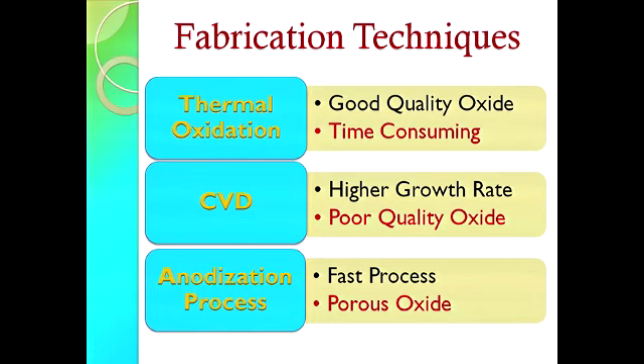We know some oxidation techniques that can be used to form silicon dioxide layer, but these techniques cannot be used to form thick silicon dioxide layer because in the first method, which is thermal oxidation, we get a good quality of silicon dioxide layer, but it's a time-consuming process. To form a thickness of 30 micrometers, it takes hundreds of hours.